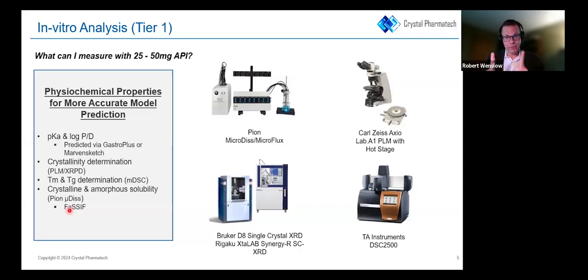And with combining those two, you can then see, well, the crystal that I found, am I at the end already, or do I have a lot of way to go? And so with that crystalline material, we want to get a highly accurate FaSSIF solubility, because this is a worst case from an oral absorption perspective. In vitro is mimicking the fasted upper GI, where most of the compounds are going to absorb. And so understanding that solubility will give you a worst case scenario of how your compound is going to orally absorb.